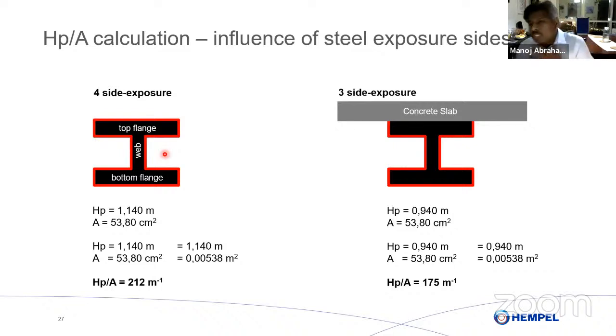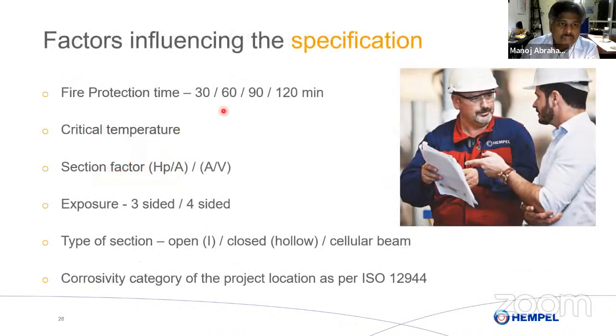So unlike your protective coating system where you say 50 microns primer, 100 microns mid coat, 50 microns top coat, no. With intumescent coatings, we have to understand the section details, the section sizes, and then we would be able to tell you what is the coating thickness required. So when you do a specification, first we need to identify what is the fire duration, the critical temperature. Normally, it is given as 550 degrees centigrade for columns and 620 degrees centigrade for beams with concrete on top, three-side exposed. Then we will calculate the section factor.